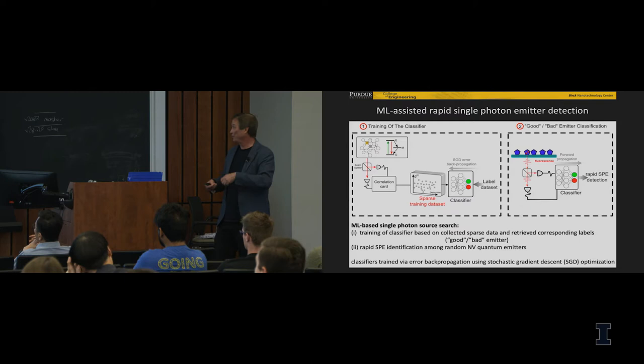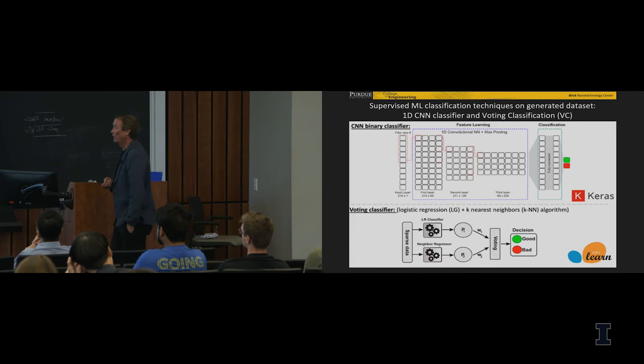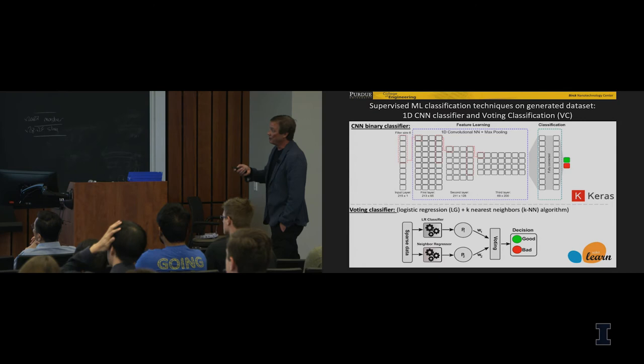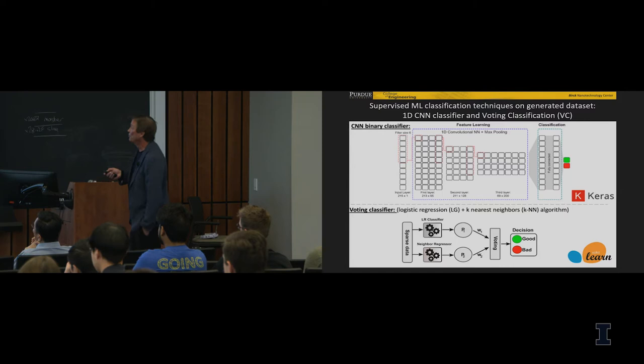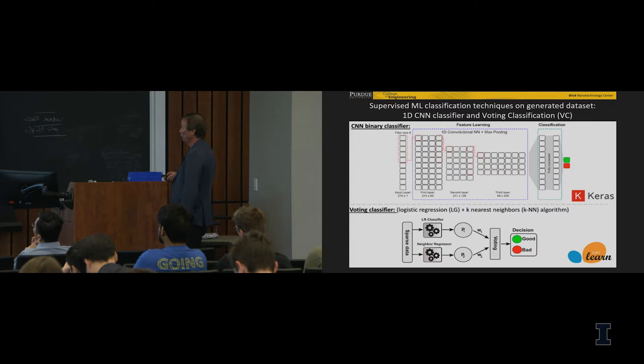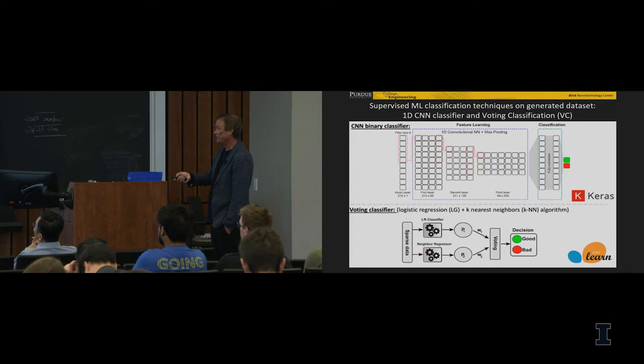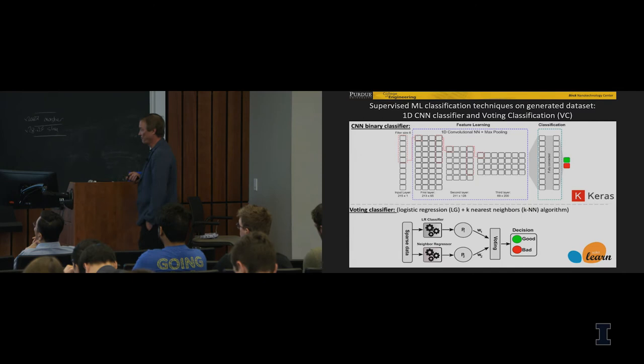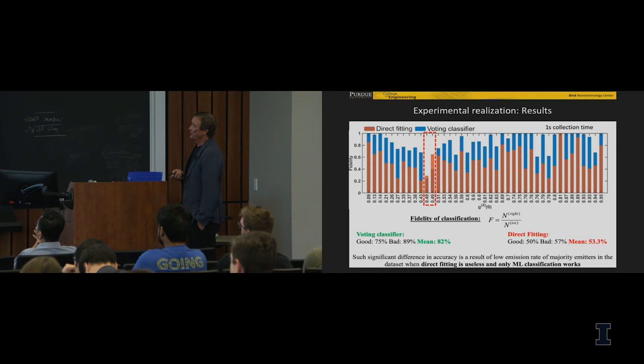So we use two different machine learning approaches I show in here too. One is based on a convolutional neural network, which consists of this input layer, three hidden convolutional layers, followed by these fully connected two layers of classification. In this case, we use this package called Keras. Another machine learning approach we used is the so-called voting classifier, which is based on logistic regression and the k-nearest neighbor algorithm. In this case, we use the scikit-learn package. And here are the results.